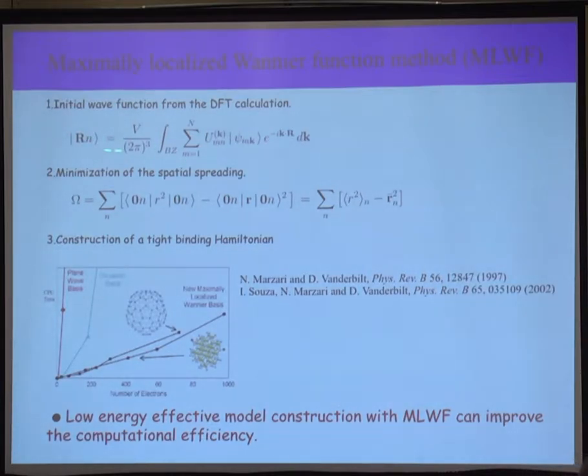The reason we call it maximally localized is that because of the unitary transformation, you have arbitrary degrees of freedom to get the Wannier orbitals, which are not fully guaranteed to be localized. So that's the reason we optimize these orbitals so that you get these Wannier orbitals to more or less close to the true atomic orbitals.